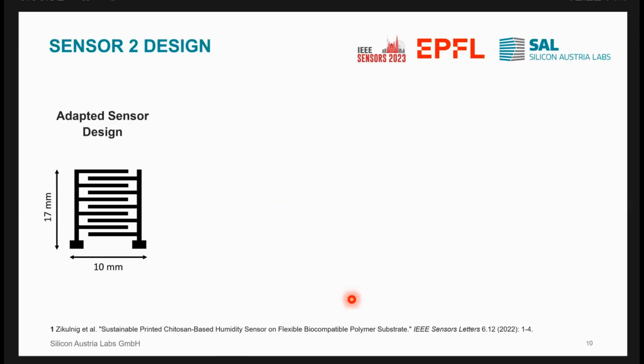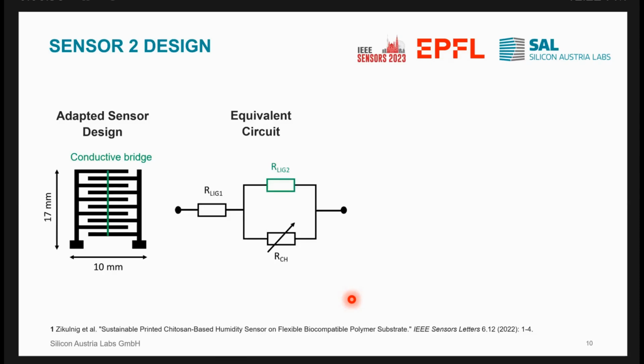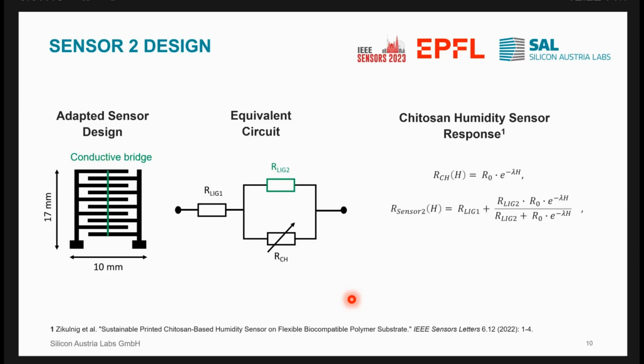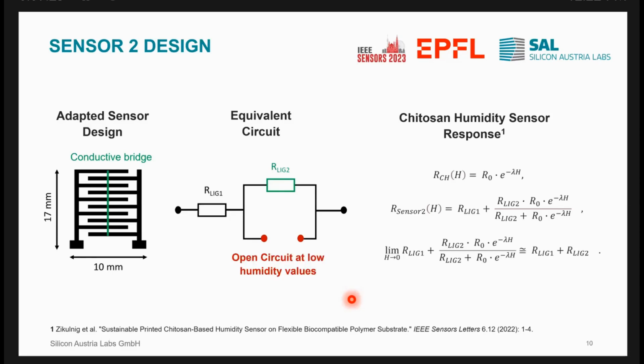So for the adapted design, which will be referred to as the sensor 2 design, we introduced a conductive bridge, which can be seen as a parallel resistance to the sensor resistance of the Chitosan. If you consider the Chitosan resistance as an exponential function, as shown before, and consider this with the parallel circuit, then when the humidity becomes too low so that you have an open circuit here, you can assume that the total sensor resistance won't go beyond a certain threshold, which is the serial resistance between the electrodes and the bridge that goes across those electrodes.